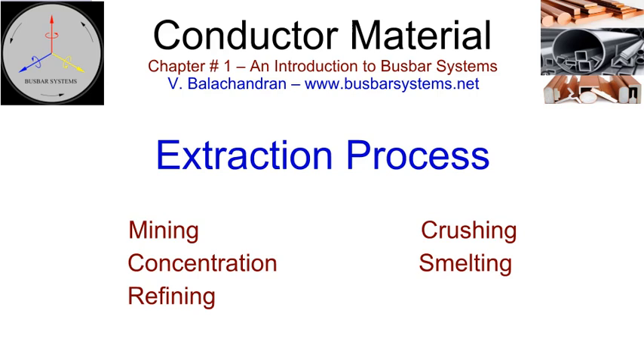Most of the manufacturers of conductors use the wire bars, cathodes, or high-purity scrap as the input raw material. These are melted in a controlled atmosphere and extruded in stages to specified dimensions. The extruded bus bars are then heat-treated for the desired temper, hardness. Copper to be used for electrical purposes should be of high purity and good conductivity. It is important to note that the conductivity of copper is highly sensitive to the impurities. A very small percentage of specific impurity will drastically alter the resistivity and consequently, the conductivity of copper. Therefore, the conductivity of copper cannot have a direct correlation to its purity.